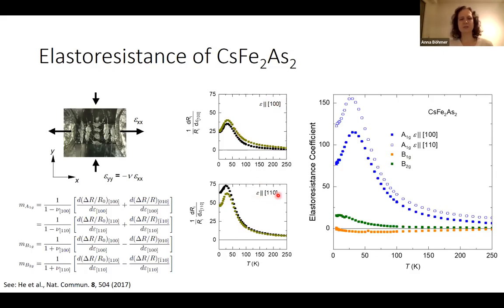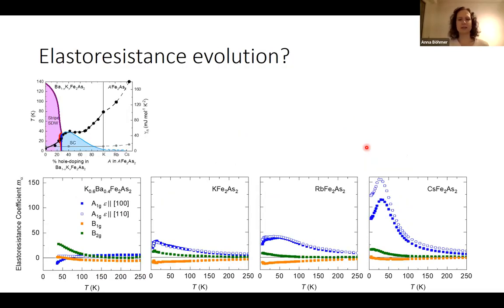And you see differences to our previous systems. There's no more sign changes here. This means that the A1G elastoresistance is dominant. It's huge here in blue. And the B1G and B2G components are rather small, much, much less than the A1G. And that was our first result. And secondly, we went to the evolution of this.